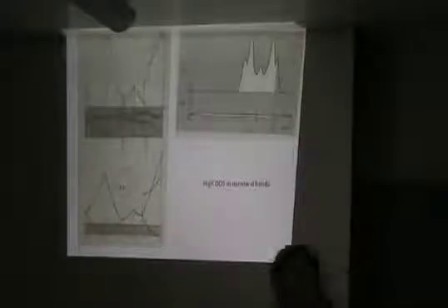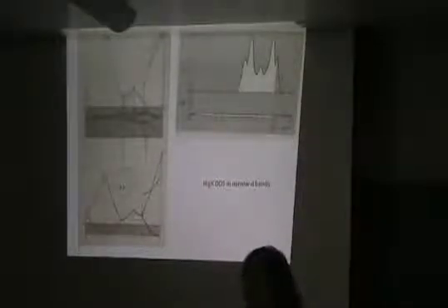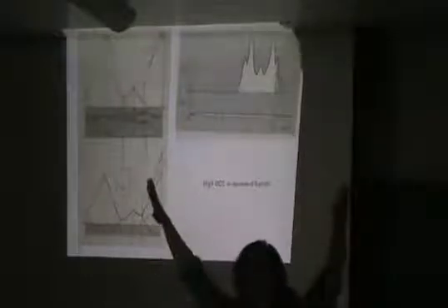You can plot the band. This is the free electron band. This is the actual band structure of gold or silver. It looks very similar. But what I want to point out are these other bands here, which are not dispersing very much. You know what that word means: as a function of momentum, they're not blowing up like this. That's called dispersion. They are very flat, which means they're very atomic-like. So these are the D bands.